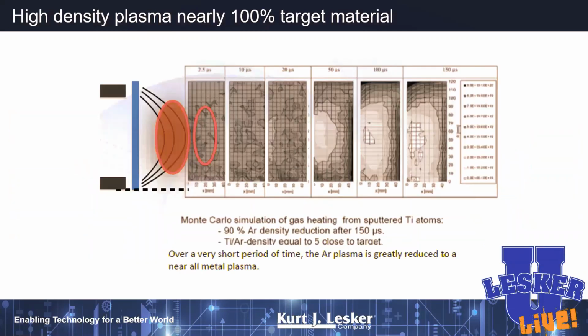So here's some time-lapse imaging, starting out at 2.5 microseconds and going up to 150 microseconds. Here's our sputter target, and here are our magnets back behind with our magnetic field. Notice in the very early stages, the plasma is dominated by argon ions. But as that plasma matures, we start to see a fairly large contribution of titanium ions. And by the time we get up to 150 microseconds, more than 90% of that plasma is dominated by titanium ions. At that point, you can see that the argon ions have been excluded from the plasma.